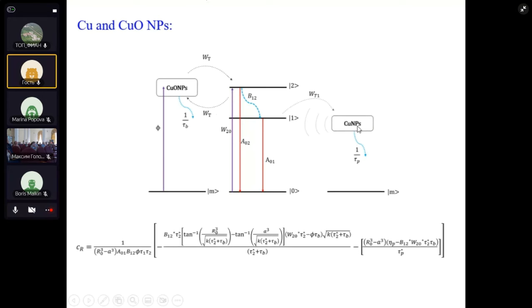And in this case, the pure copper metallic nanoparticles lie very much below. And in this case, we may have a local field enhancement due to the copper nanoparticles' plasmon, but also energy transfer from the europium ion to the copper metallic nanoparticles. And in the appropriate system of rate equations, we have to take into account the balance between all these processes. If we take out one of these channels, the copper oxide or the pure copper nanoparticles, then the theoretical predictions are not good.